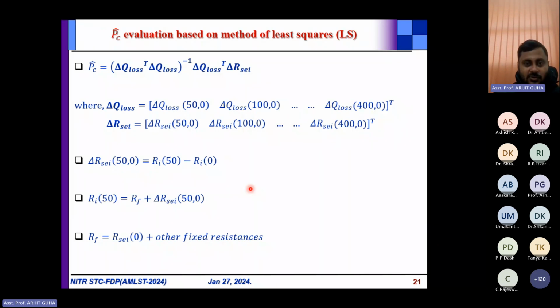In order to estimate PC, we have used the very popular method called the method of least squares. This is very popular when we go for curve fitting. If you see, PC has been written in such a way that these bold symbols denote a vector, right? So this is basically a vector, written in a row vector form with transpose. Here delta Q loss has all these components, and delta R sei has all these components. Here these 50, 100, 400 are different stages of the battery aging, right?